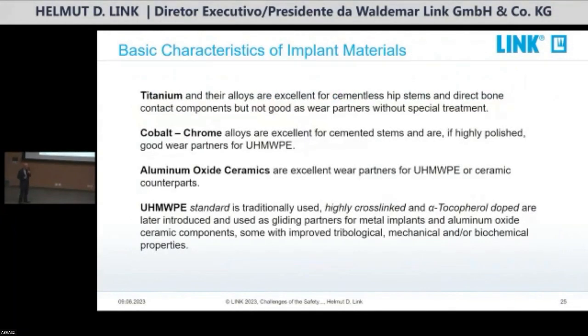Now, in general, titanium and its alloys are excellent for cementless hip stems and direct bone contact components, but not as good for wear partners. Cobalt chrome alloys are excellent for cemented stems and are, if highly polished, good wear partners for poly. Aluminum oxide ceramics are excellent wear partners for poly or ceramic counterparts. And the poly, again, is divided into traditional poly, highly cross-linked poly, and alpha tocopherol or vitamin E doped, which was introduced much later but is nowadays a very popular poly, because the vitamin E grabs the free radicals, the oxygen, and at least prolongs the life, to be careful in statements, prolongs the life of the poly.